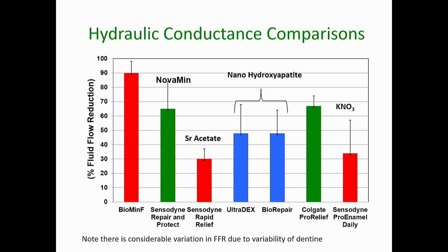We measured the fluid flow through dentine discs before and after treatment with different toothpastes, and this slide shows a summary of the different data. Here on the extreme left we have the Biomin F, which is giving about a 90% reduction in fluid flow through the tubules of a dentine disc. The Novamin toothpaste, the Sensodyne Repair and Protect, gives quite a good performance. It's about 65%. The Colgate Pro Relief, which is the other leading brand, gives you just under 70%.